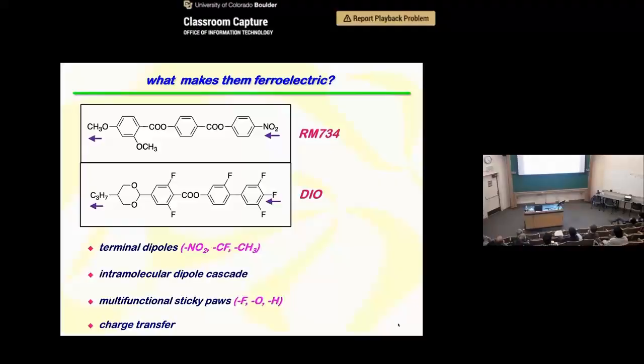Okay, so then the question is, what's special about these that somehow is lacking in the first 500,000? So I think the main features are here. Both of these molecules have terminal dipoles that point in the same direction and are very, very close to the ends of the molecule. So if you put this molecule end to end, then you get strong dipole-dipole interactions between these end groups. So that's a commonality.